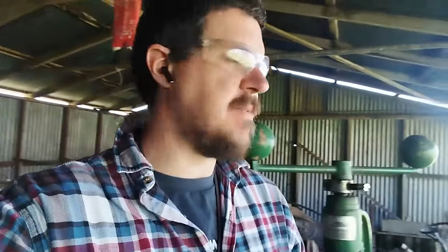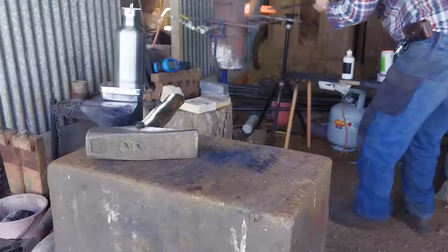So you can see I've consolidated one end partially, but we're now getting it up to that temperature where the slag that's still in there really wants to become liquid. So this is the real risk of it falling apart. I managed to break off a chunk of the slag in the first heat. It weren't quite hot enough, but at the same time, most of that was just slag that was encrusted on the outside. So the bloom's going to start getting a little softer now because it's quite small, and there's not really much mass to help hold it together, so I have to be careful. Little delicate hits, small rounds, only a few hits per round, and we'll get there.